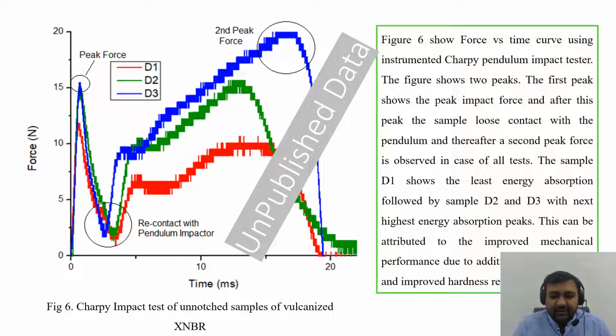This figure shows the results of the Charpy impact test of the samples of vulcanized XNBR. And this figure shows two peaks. The first peak shows the peak impact force, and after this peak the sample loses contact with the pendulum, and thereafter a second peak force is observed in case of all tests. The sample D3 with the highest hardness shows the highest energy absorption peak, and with the reduction in hardness the peaks are also reduced.